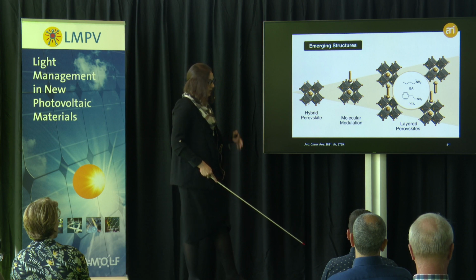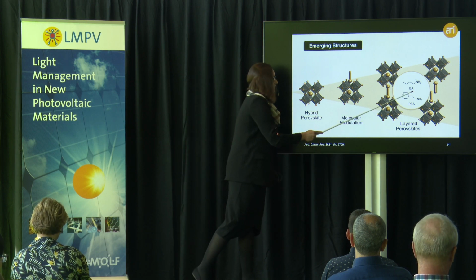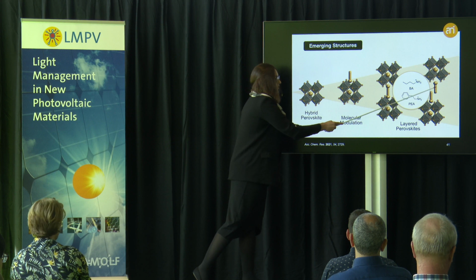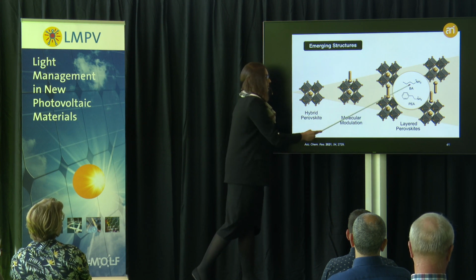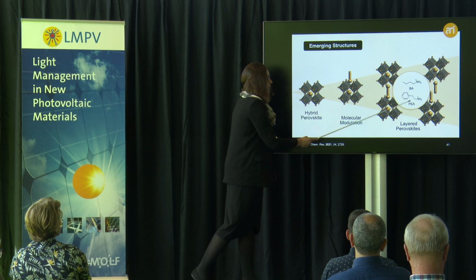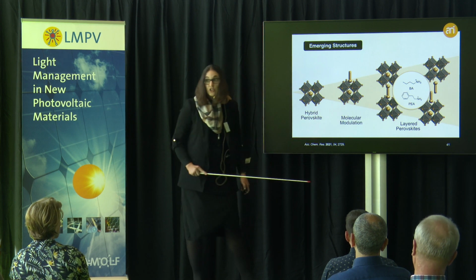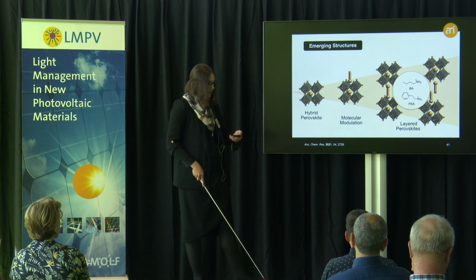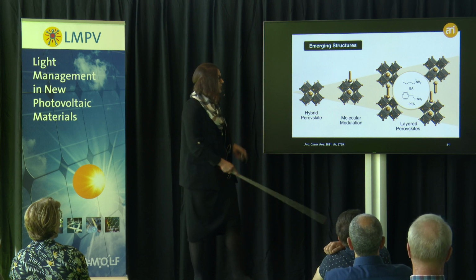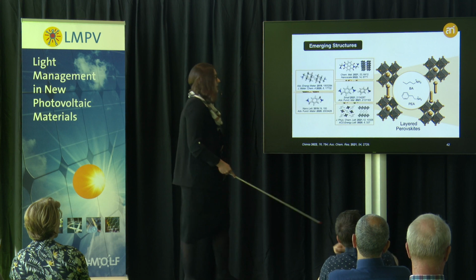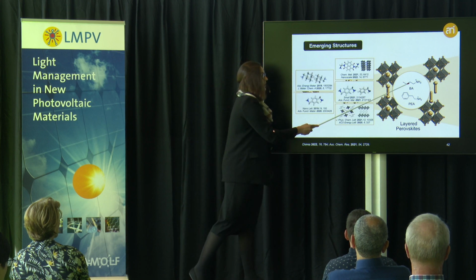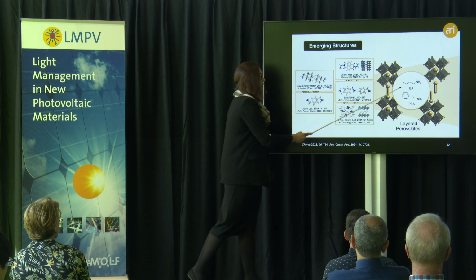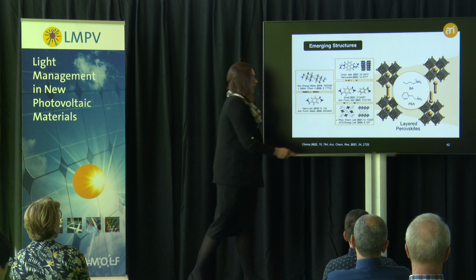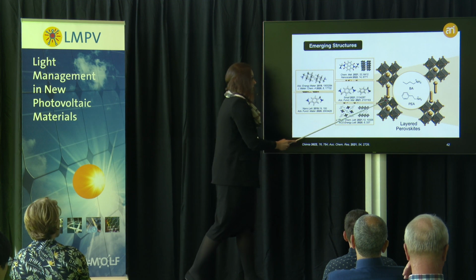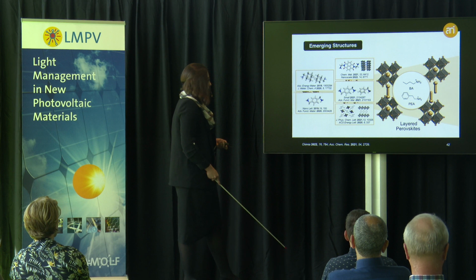for maybe those that are more interested in the chemistry in the room, being these butyl ammonium or phenylethyl ammonium-based systems as these spacer moieties, we have tried to extend and further analyze in terms of extending the range of possibilities and the functionalities on these particular components, involving a number of different organic spacer moieties, some of which are illustrated here. So for instance, strengthening these van der Waals interactions by introducing these carbocyclic elements, or tailoring further these aromatic interactions in order to achieve not only the Ruddlesden-Popper, but different Dion-Jacobson-based phases.